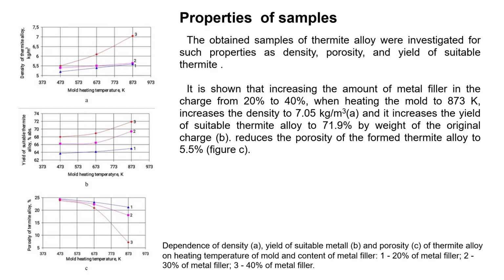It is shown that increasing the amount of metal filler in the charge from 20% to 40% when heating the mold to 873 kelvins increases the yield of suitable thermite alloy to 71.9% by weight of the original charge. It increases the density to 7.05 kg per cubic meter and reduces the porosity of the formed thermite alloy to 5.5%.